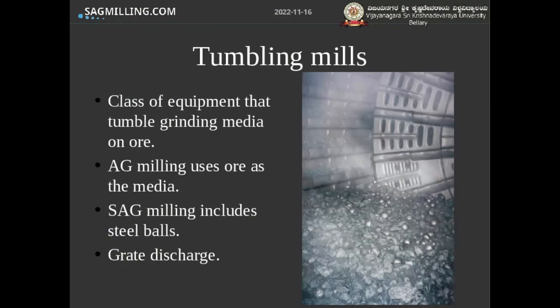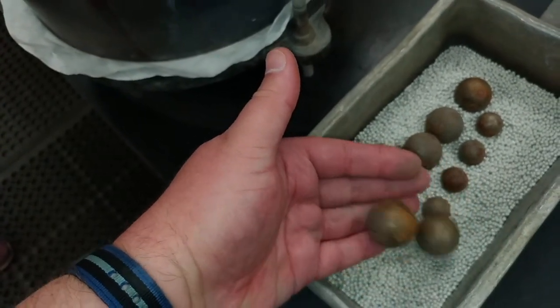Where you are on this spectrum can dictate the type of mill you're going to end up installing. Typically, AG mills are cheaper to run but they're larger and have a higher capital cost. SAG mills are smaller with a lower capital cost but a higher operating cost. Ball mills, for reasons I won't get into, are only really applicable to material feed below about one or two millimeters — they're not suited for really coarse particles.